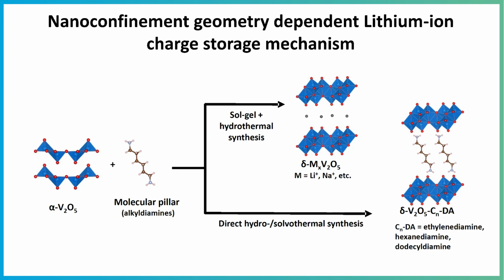How we did this was we inserted organic molecules, alkyldiamines, between these V2O5 layers. What these pillar molecules do is act as spacers, so they hold these V2O5 layers apart. We intercalated, or let's say inserted, diammoniums of different chain lengths, and by doing so we created vanadium pentoxides with different interlayer spacings.